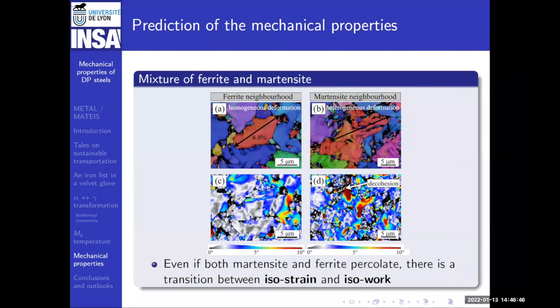What we noticed is that neither isostrain nor isowork works well. And if we want to understand what's happening, we have to look at the evolving microstructure using EBSD, where you can see the local misorientation, and you can see that at the beginning, for fairly low deformation, martensite and ferrite deform the same way. But at some point, martensite fractures.